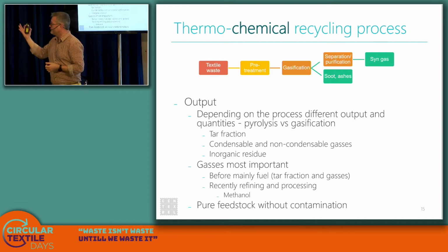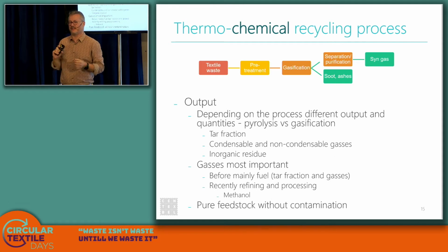What they actually do is they heat up with gasification. You have pyrolysis, they heat up at a lower temperature, 500, 600 degrees. And then you get out an oil fraction that is used as fuel. And you get out gases that can also be sometimes fuel, but also feedstock for new chemicals that can be used within the chemical industry or artificial material production.